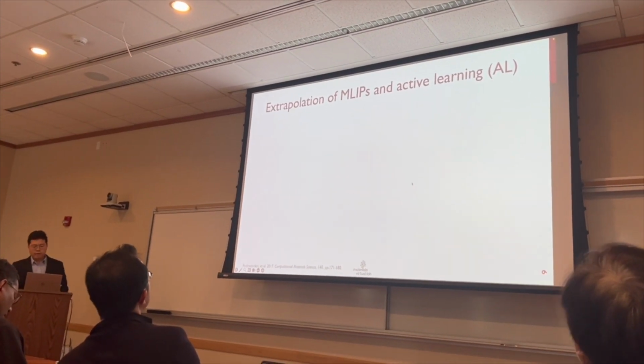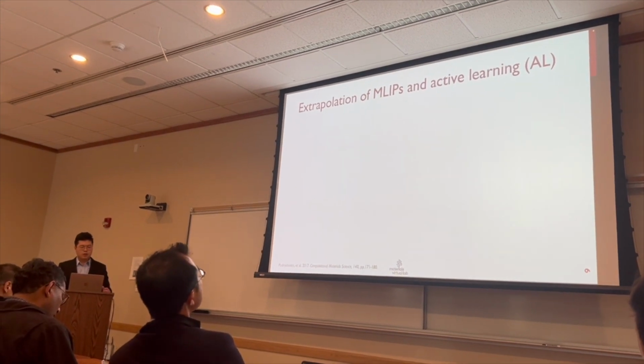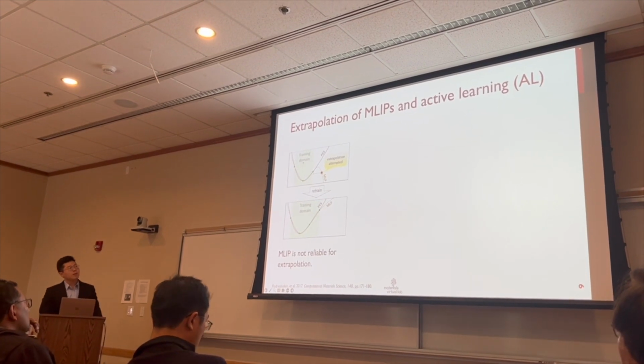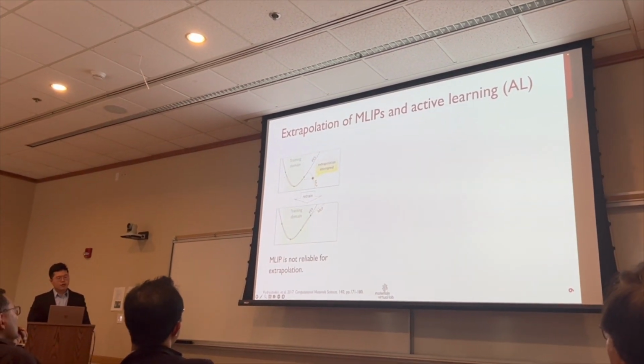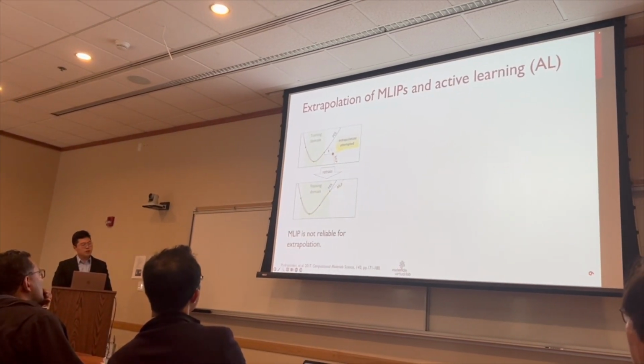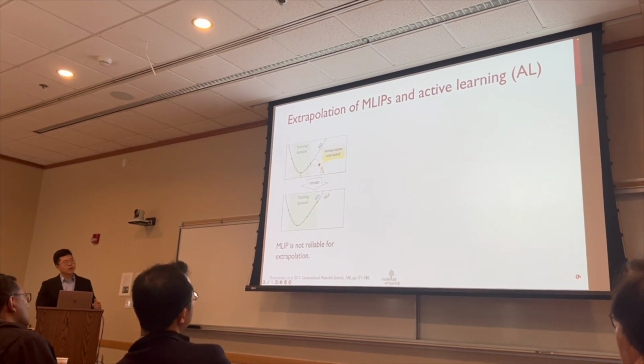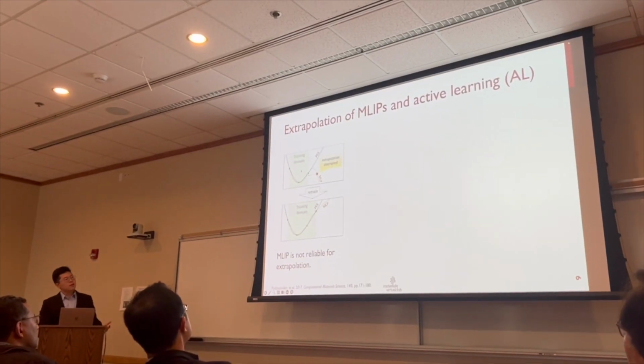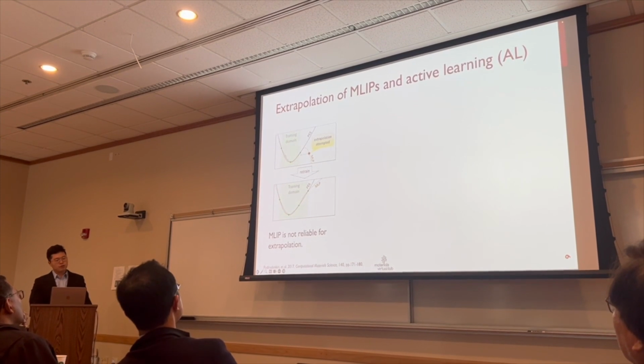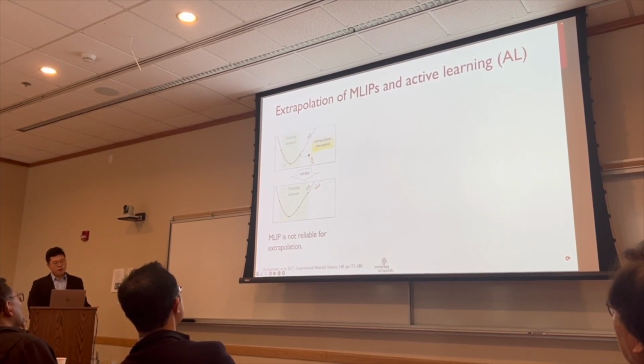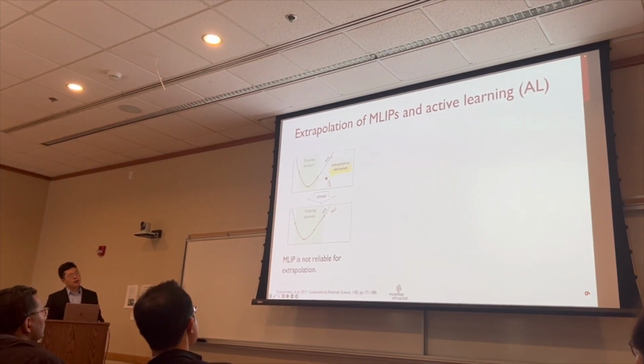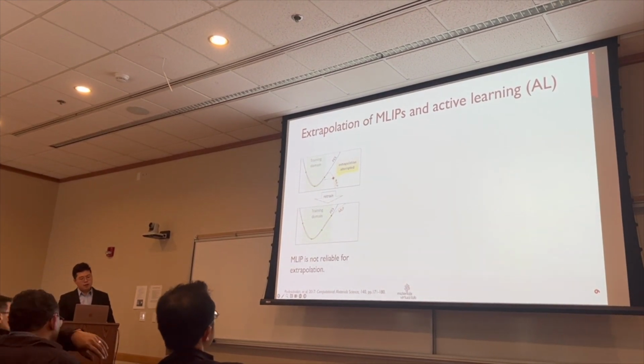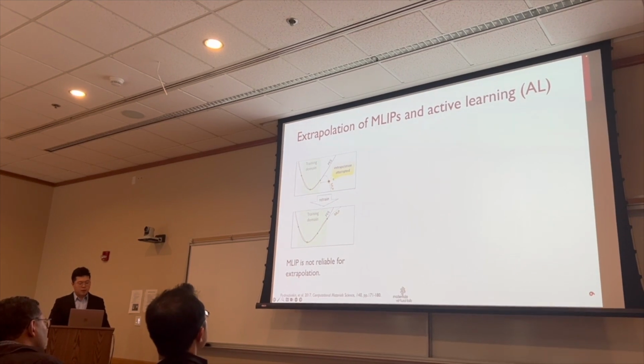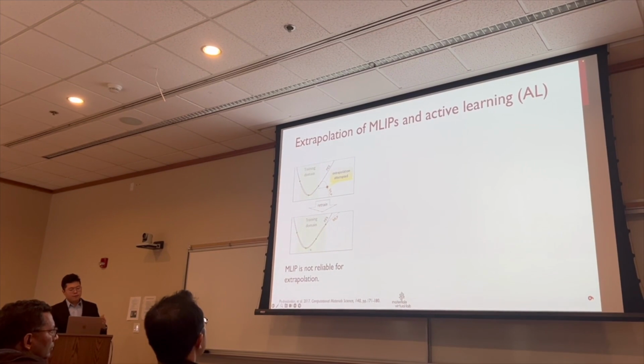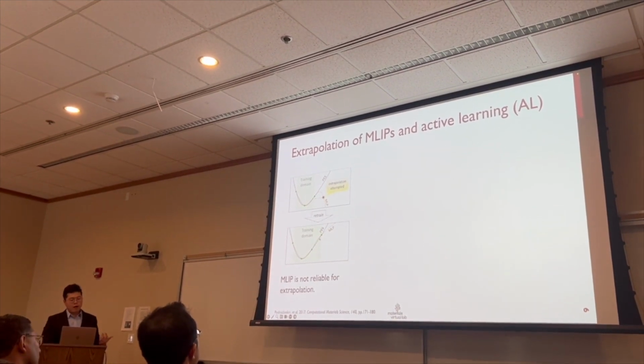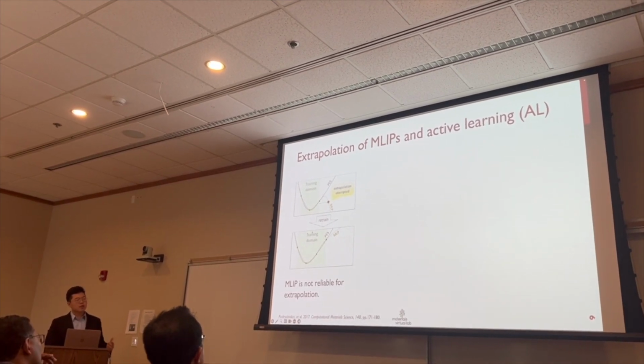And I also want to mention a very important challenge for all machine learning interatomic potentials, which is so-called extrapolation. Here in this schematic diagram, the black curve represents the ground truth potential energy surface, usually from DFT, and the orange curve, which is dashed, represents the predicted result from a machine learning interatomic potential. You can see that MLIPs have very good matching with the ground truth result for prediction of structures in the training domain. However, for prediction of structures that are out of the training domain, the so-called extrapolation behavior will be attempted, and the prediction result is not guaranteed to be reliable. So that's why it's crucial for our training set to have a diverse coverage of configurations for us to have a reliable machine learning interatomic potential for diverse simulation scenarios.